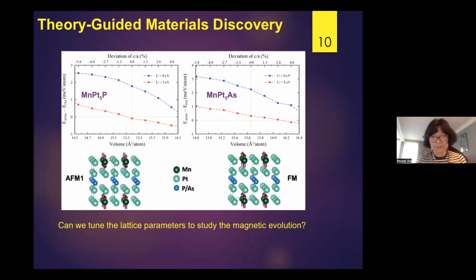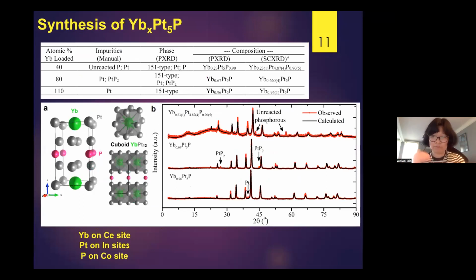And we studied the chromium, iron, chromium, manganese, iron, even cobalt, and we didn't find any superconductivity. So then we said, okay, let's move to the rare earths. So for the rare earths, we also did the whole family, but we found a very interesting compound. That's ytterbium platinum 5 phosphorus.